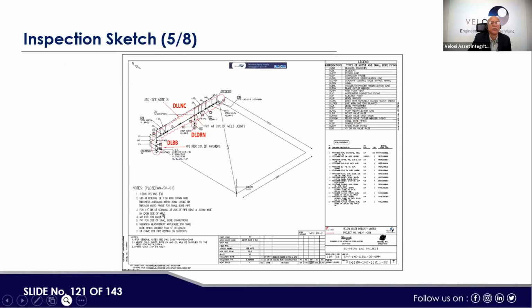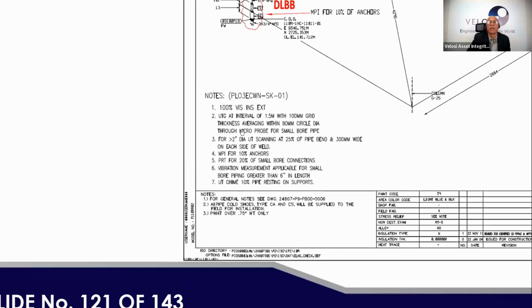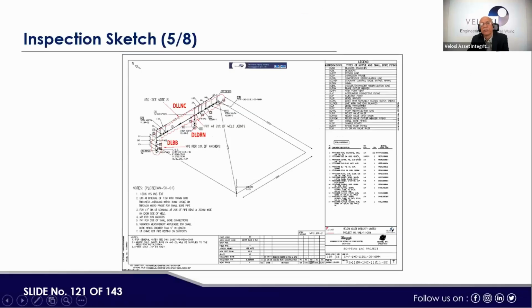For example, 100% visual inspection, UT gauging at an interval of 1.5 meter with 100 mm grid thickness average. Then for greater than 2 inch diameter, UT scanning at 25% of piping bends. Then MPI for 10% anchors, PRT for 20% of the small bore connections, vibration measurement applicable for the small bore piping greater than 6 inch length. Then UT chime 10% piping resting on supports. These techniques are identified to cover the complete piping system, including the dead legs.